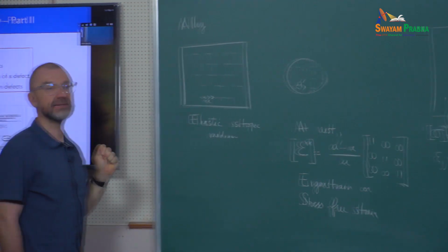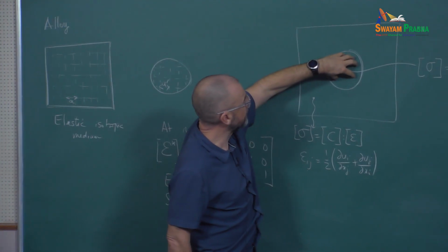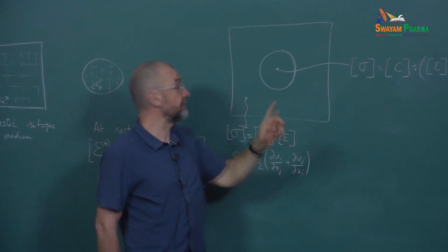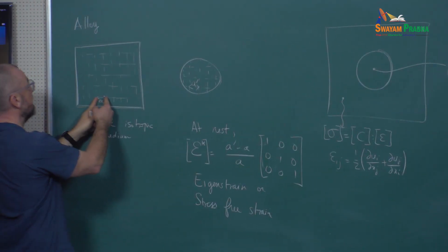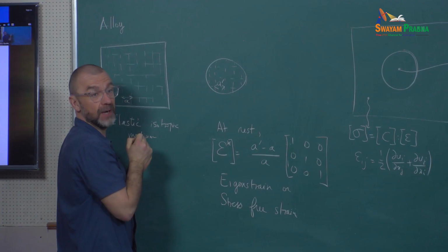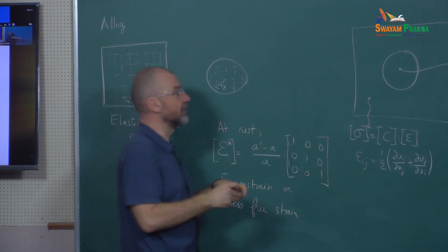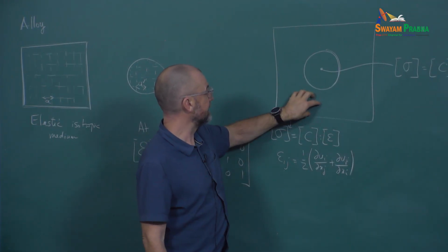Am I making sense or not? Yeah, exactly. To bring the system inside the precipitate to zero stress, you need to have a deformation inside that takes the A lattice parameter to A prime. So you need to have a finite deformation to be at zero stress. So the reference state here is the matrix itself.